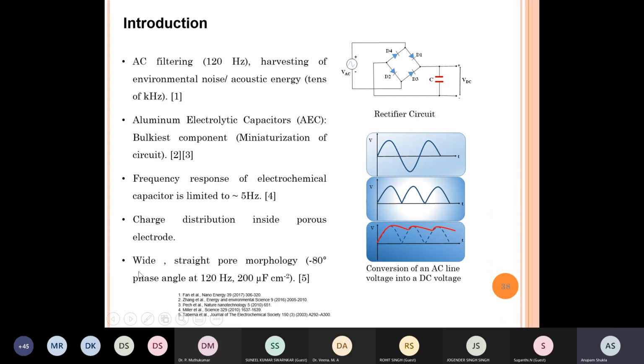What they found was that porous electrolyte resistance increases because the pores are narrow and also tortuous. So if one can go with wide straight pore morphology, then it is possible to get a phase angle of -90. By the way, capacitive behavior is -90-degree phase angle. Okay, so as soon as you start going away from -90 degrees in an impedance plot, then you move away from the capacitor.